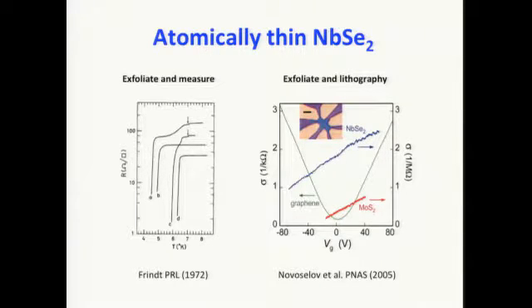But some 30 years later, Novoselov reported in his famous paper in PNAS in 2005. At this time, they tried to do a better job, but got worse results. They exfoliated a monolayer or bilayer of niobium selenide on top of silicon, and then tried to put down electrodes with lithography techniques. What they got is that these films have a resistance of about a megaohm. So basically, it's like an insulator. What we know nowadays is that the material is not so stable. You cannot really expose it to oxygen, to ambient, for that long. You certainly cannot do lithography on it. So it's bad for the material.